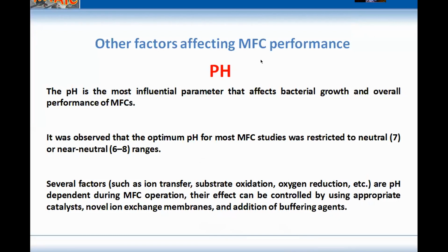Among the other factors affecting microbial fuel cell performance, pH is a very important parameter that affects bacterial growth and the overall performance of the microbial fuel cell. It's well observed that the optimal pH for the best microbial fuel cell performance was restricted to the neutral or near neutral range from 6 to 8. And also, several factors such as ion transfer, substrate oxidation, or oxygen reduction are pH dependent during microbial fuel cell operation. Their effect can be controlled by using an appropriate catalyst or novel ion exchange membrane, or by adding some buffering agent.